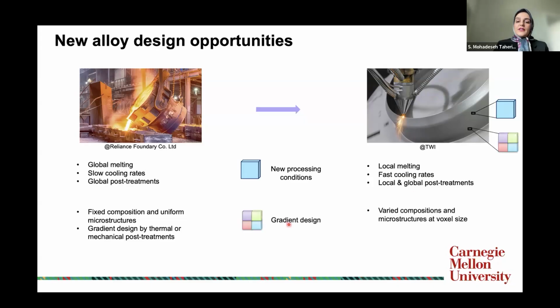The other opportunity is that we can have gradient alloys. Here, when you choose the composition to be melted and you choose the processing, the composition and microstructure, which is what you can see under the microscope of alloys, are fixed through the component. And if you want to change it systematically, that I will tell you why, then you have to do systematic post-heat treatment, mechanical or thermal.